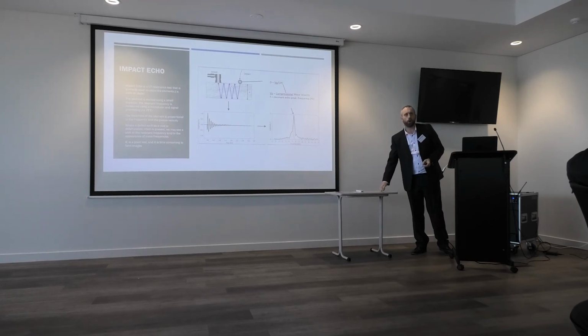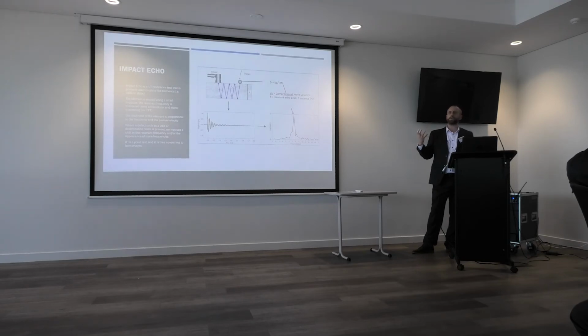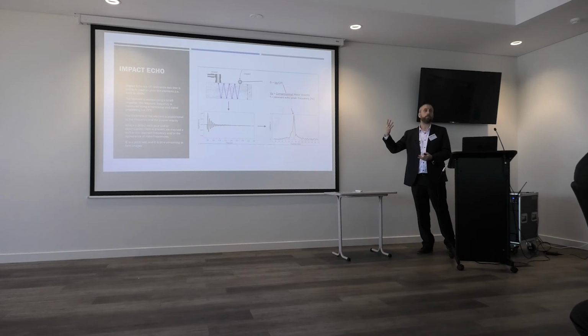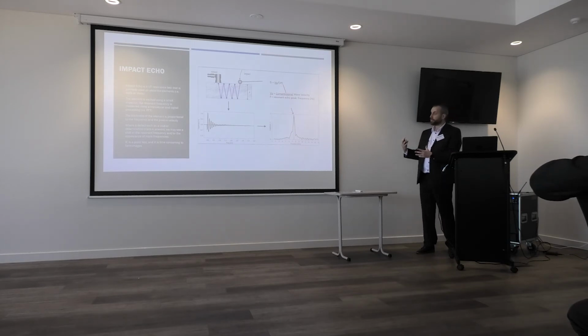So if I knock on the table there, I can hear the frequency coming off of it. And we know instinctively, by the way that we deal with the world around us, that if that was thicker, that frequency would be lower, and if it was thinner, the frequency would be higher. Okay, so that's effectively what impact echo is. We knock on the concrete and we get our resonant frequency, and then that correlates to the thickness of the concrete, okay? And we do that using some solenoids to impact on the surface. We use a transducer to pick up the resonant frequency, and then we pass it through a fast Fourier transform to estimate what the resonant frequency is.